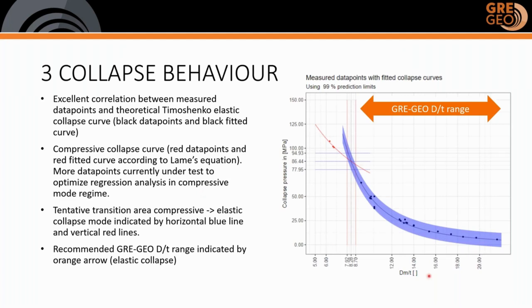When we started to test collapse behavior, we observed two different failure regimes that are also observed in steel casings. One is the compressive collapse dictated by exceeding the hoop strength, and this occurs at thick-walled casings with a low D/T value. In the plot, you see the collapse pressure against the D/T ratio. The red points you see over here are related to compressive collapse, and the fitted line is the line according to Lamé's equation. The elastic collapse is indicated by the black points, so all the points are measurement points.